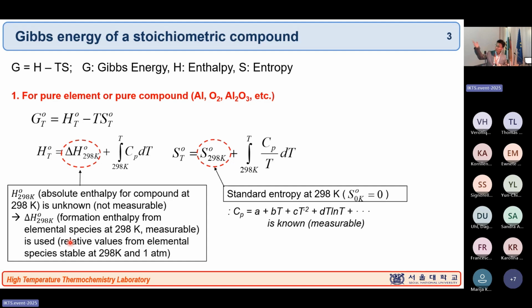That's why H starts from delta H298, which is called the standard enthalpy of formation from all the elemental species we can find in the periodic table, which are stable at room temperature and room pressure conditions, which we can easily obtain. So they mixed, for example, aluminum and oxygen together to make alumina, and during that, you can measure the enthalpy change.